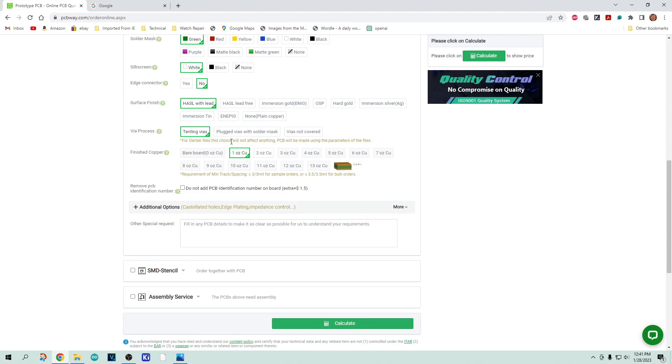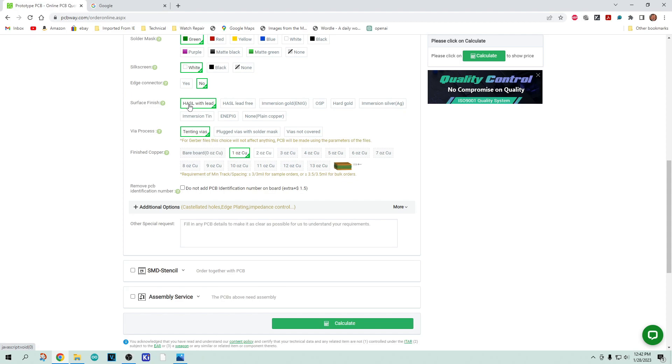And remember I told you that copper oxidizes so you want to coat it with something, and the cheapest thing to coat it with is just solder. Just put solder on it and then the solder protects it from oxidizing. And so HASL is Hot Air Solder Leveled with lead. So this is lead solder and what they do is they dunk the PC board in lead solder and then they take an industrial hair dryer and they blow it so that it levels off. They kind of blow off all of the metal and it levels it as much as air can level it. It's not a perfect leveling but it's not too bad, and they use this jet of hot air to level the plating that they've just put on. You could choose if you don't like lead you could tell it to use lead-free solder.